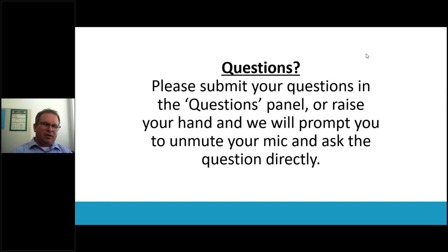Yeah, thank you for this interesting question. Yes, we did experiments on that, for example, by investigating GDLs that were aged in this way with imaging techniques, and we could see that they tend to retain water to a much greater extent than fresh material.